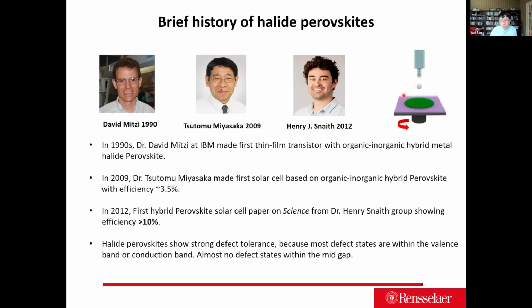And then the material shows a great defect tolerance. It effectively means that if you spin coat the material without bothering the MBE or solution grow it, because of the nature of the material, they automatically push all the defect states outside the band gap. So there are almost no defect states in the mid gap, which means the material has really high quantum yield. It's a good solar cell material. It's a good LED material. Many of the chemists became very excited about it.